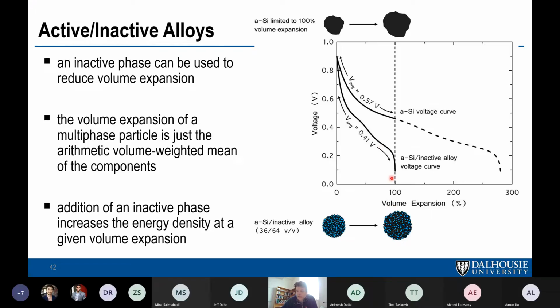And again, this is what Jeff mentioned in the last lecture. A strategy is to have graphite with these alloy particles encapsulated within the graphite. And then you have a completely active particle, and maybe even pure silicon inside. So that's one strategy to reduce volume expansion and yet still use all active materials. Okay, thanks.